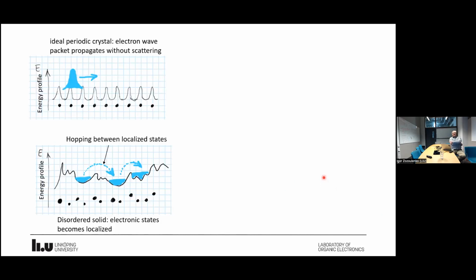So what happens with the hopping transport? The upper picture represents an ideal periodic structure. This is exactly what we discussed: a wave packet which in principle would propagate without any scattering through an ideal system. However, imagine that instead we have a disordered solid. This energy profile shows the energy structure of the disordered solid. Instead of a nice periodic structure, you have a very disordered structure. According to quantum mechanics, the electronic states will be localized due to this potential profile. And then electrons can jump between these localized states.